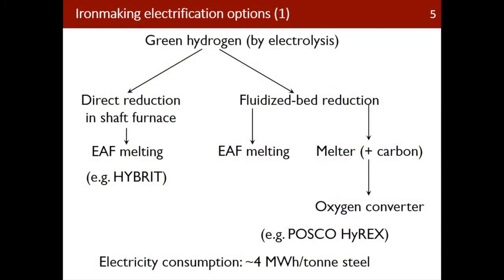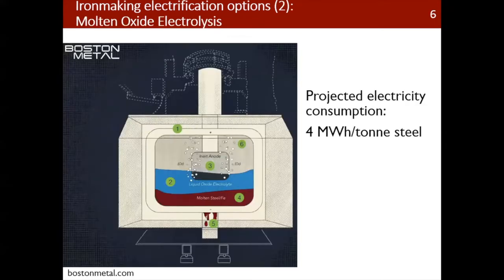Something that is worth noting here is the overall electricity consumption, which is largely that to make the hydrogen, and that comes out at one order of magnitude more than when we recycle steel. This is now 4 megawatt hours per ton of steel in round terms. An alternative technology then is to do direct electrolysis. So this is rather like the process used to make aluminum. This is currently running at pilot scale, and it's a process being developed by Boston Metal. So it's all in one unit. So the heat is generated by mostly ohmic heating, oxygen produced at the anode and iron at the cathode, and the projected electricity consumption is 4 megawatt hours per ton of steel, seemingly an inescapable number.